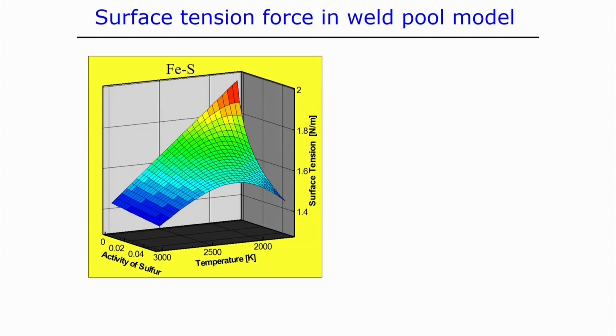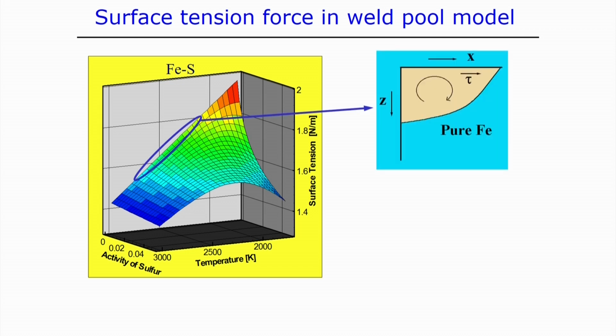We can see with respect to the temperature, at a certain optimum temperature, the surface tension force is maximum for a fixed amount of the surface active element. In other cases, with a combined effect of a very small amount of surface active element and probably at high temperature, the surface tension force becomes maximum. So, this three dimensional figure will be better explained in this way: in this case the surface active element is low, so a very small amount of the surface active elements, or I can say there are no surface active elements.